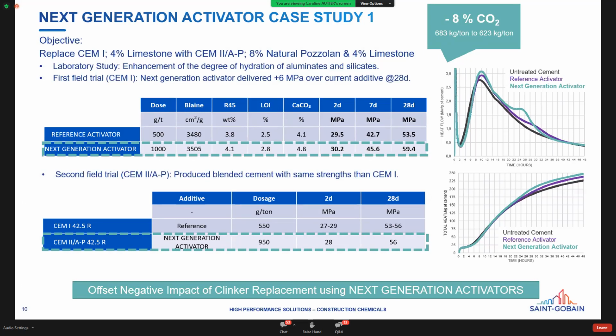Prior laboratory trials were performed to customize the activator composition. The right graph represents the influence of the reference additives and the selected next generation activator on the paste flow over the first hours of hydration. You can see that the last product allows to better increase the intensity of the main peak, corresponding to the calcium silicate hydration, and the second peak, corresponding to the sulfate depletion point. Consequently, an additional gain is observed on the total heat presented on the bottom right graph. It corresponds to the overall hydration. It means that our next generation activator had a higher influence on the cement hydration compared to the reference activator.